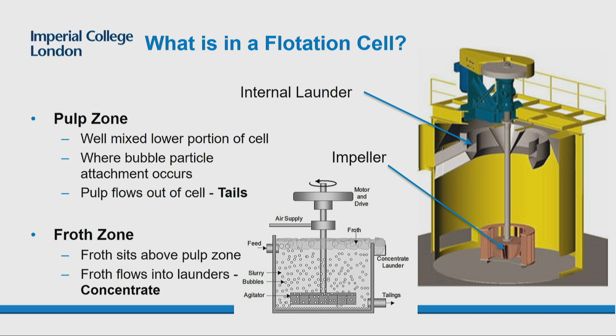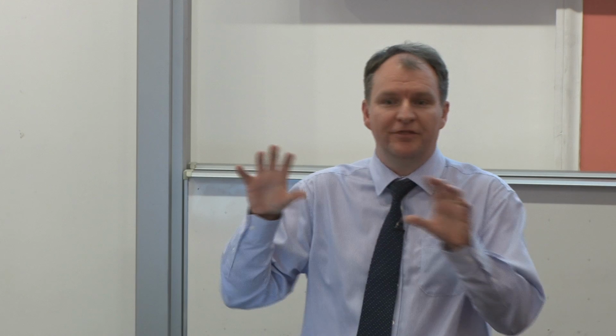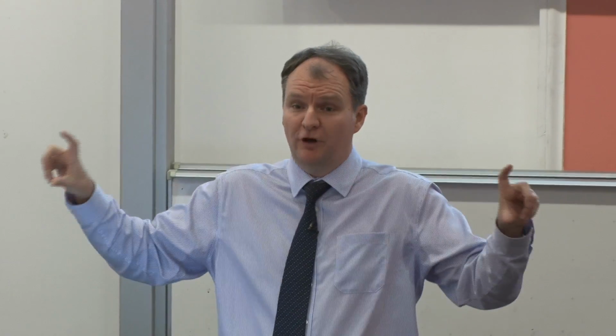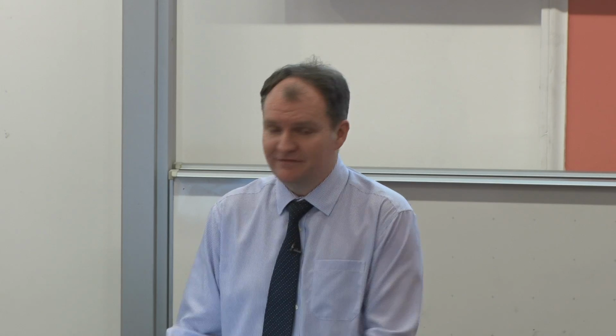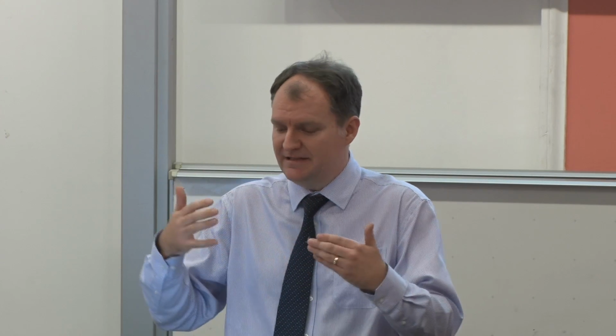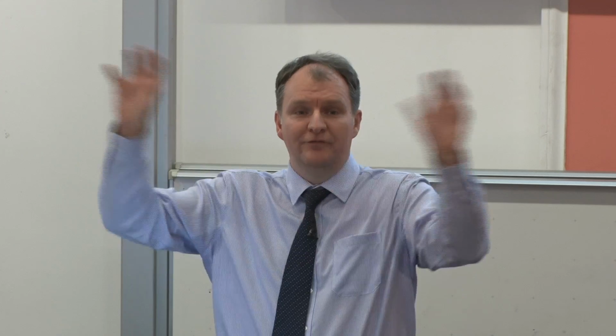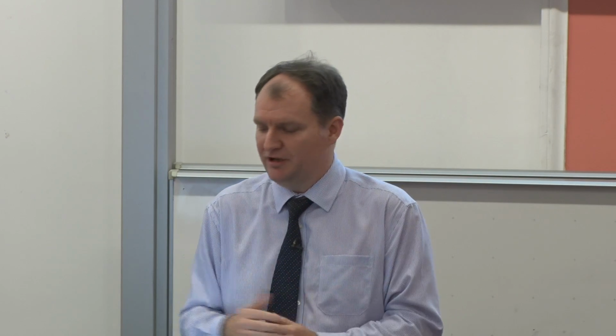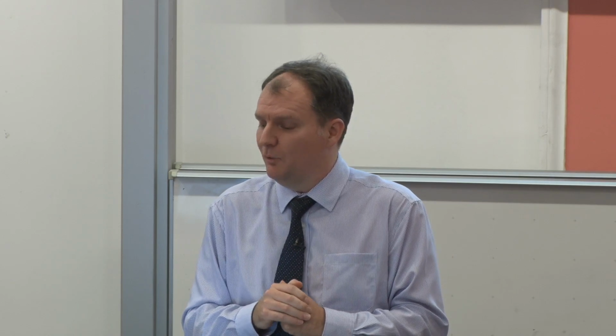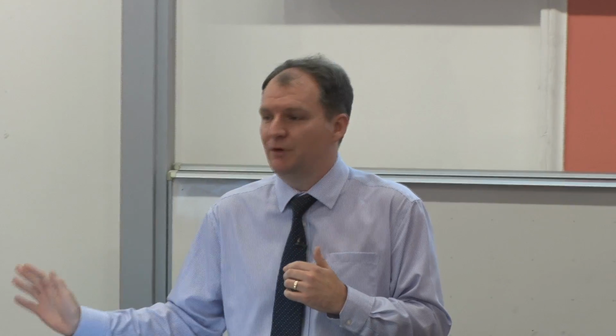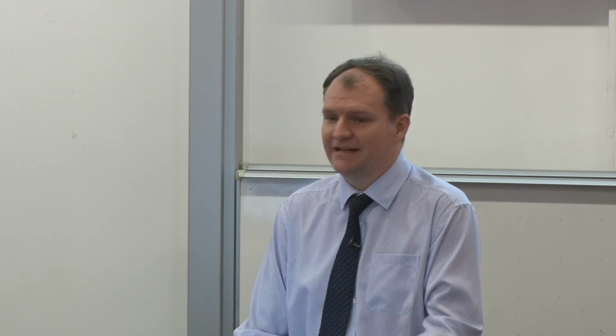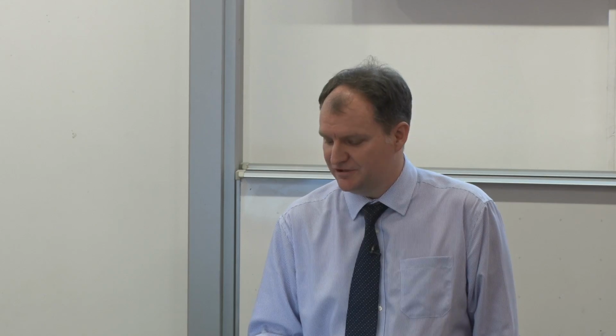These, of course, then rise up to the surface of the cell and form a froth layer at the top. And this froth is actually very important for the performance of the cell, and we'll get to that in a minute. But this froth then overflows, and that is what is collected as your concentrate, the product from these cells, whereas the material that flows out of the bottom of these cells hopefully contains substantially less of the material you want, and so that is the tailings or waste stream from the cell. And these cells work in series.